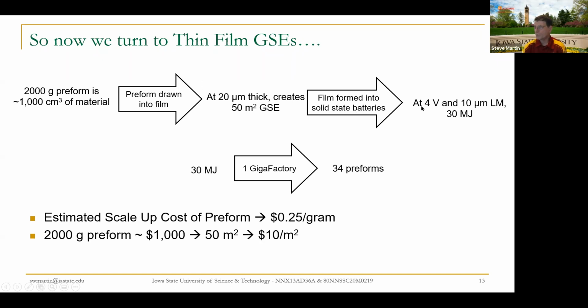You've got 4 volts, and you have used 10 microns of lithium, the chemistry and charge. You get about 30 megajoules of energy out of every one preform. Well, 30 megajoules dividing into 1 gigawatt makes about 34 preforms. So you could make a gigawatt every day by having 34 draw towers pulling 50 square meters of glass every day. Glasses are relatively cheap.